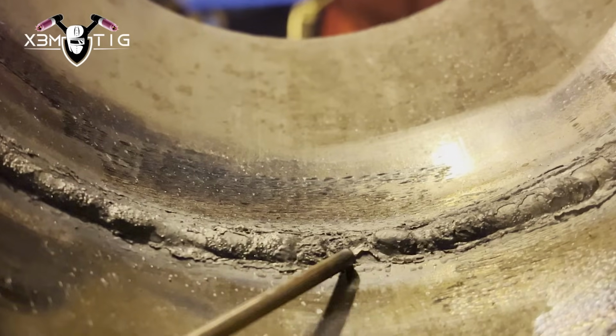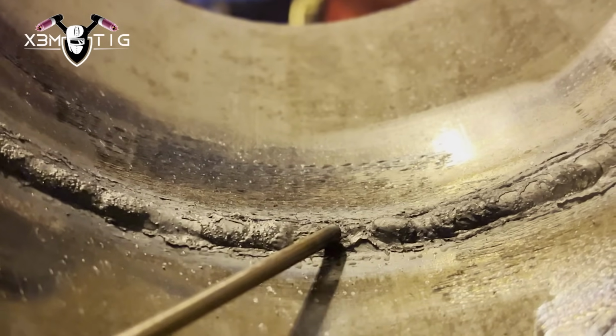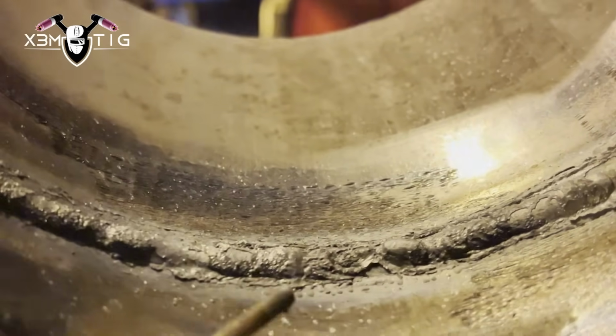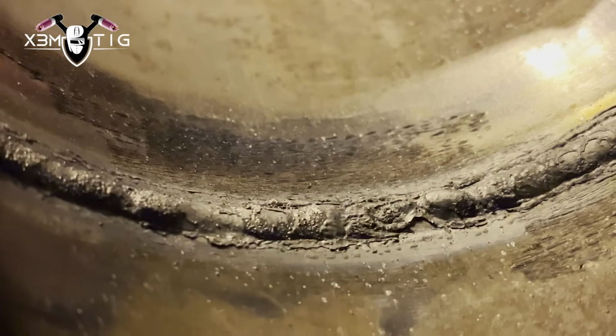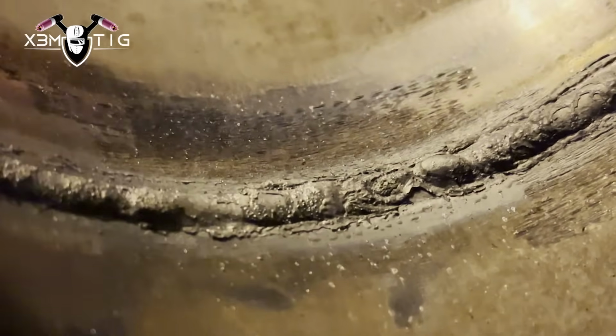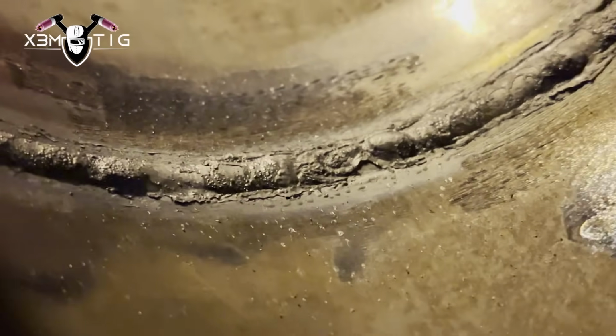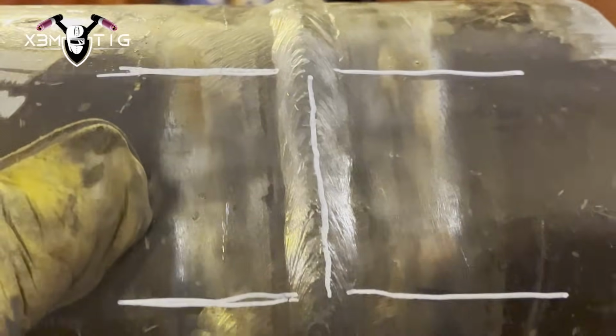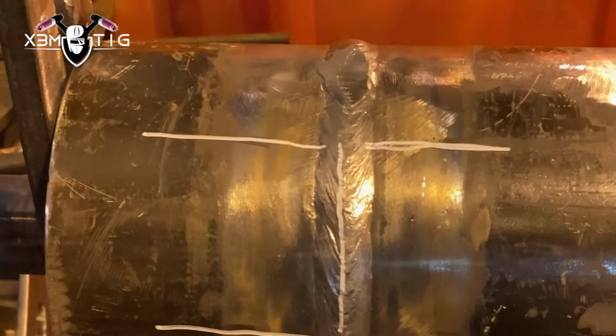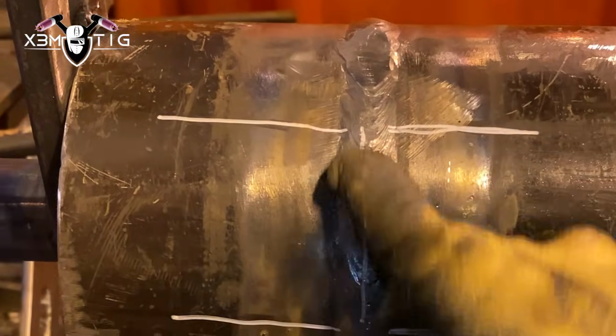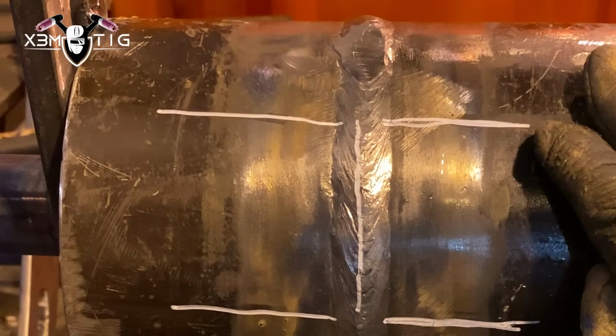This is a burn through. There should be lots of porosity inside. You can see by the burn through there's several factors that cause it: excessive heat input, inadequate joint preparation, incorrect welding technique. So in this case it's gonna be incorrect welding technique. That means you're holding on to one spot for too long. Your travel speed is too slow. So I'm gonna show you how to fix it.